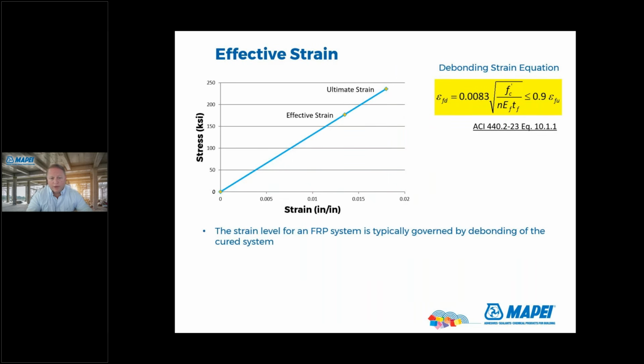Now, as it relates to effective strain, the strain level for an FRP system is typically governed by the debonding of the cured system. So in practice, and what research from universities has shown, is that the FRP is going to debond before it reaches its ultimate strain. And so the ACI committee derived strain equations to limit the amount of strain that can be utilized. We just don't want the manufacturers like MAPEI to be getting callbacks like, we put up the FRP and now it's starting to come off. So these strain equations limit that strain.